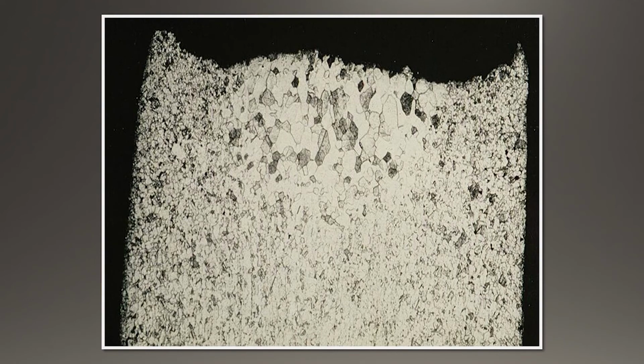Here's a cross-section of a copper wire that was etched to show the grain boundaries. And as you can see near the crack, there are some very large grains. What you're looking at is a duplex grain structure that was caused by some heating of the rod. That took place during the hot welding of the rod. So this happens to be what you would call a weld break that was caused by the improper conditions during the welding process.